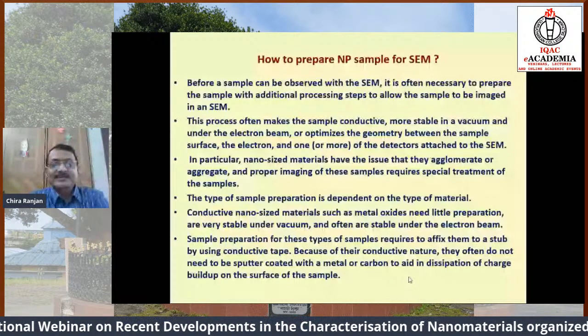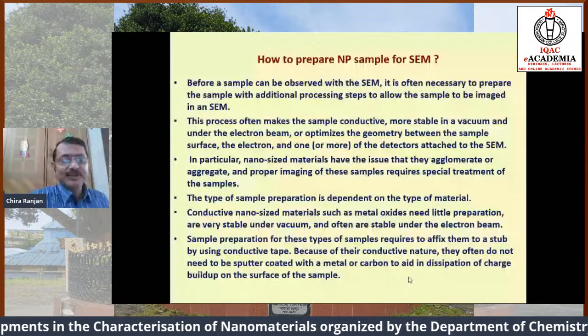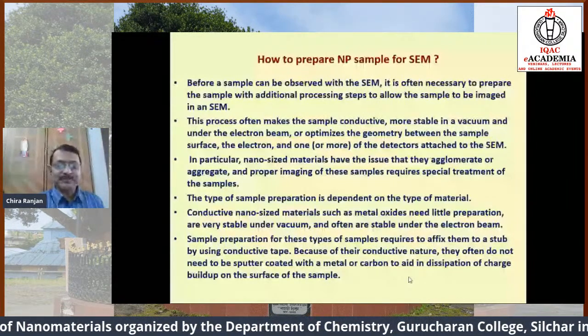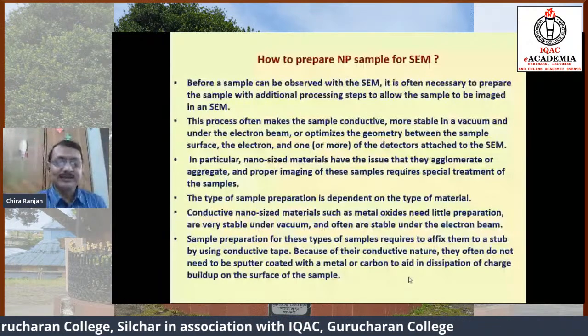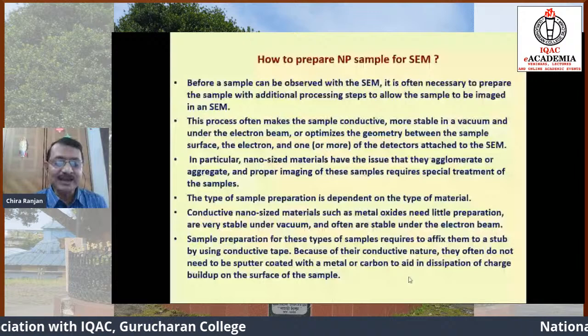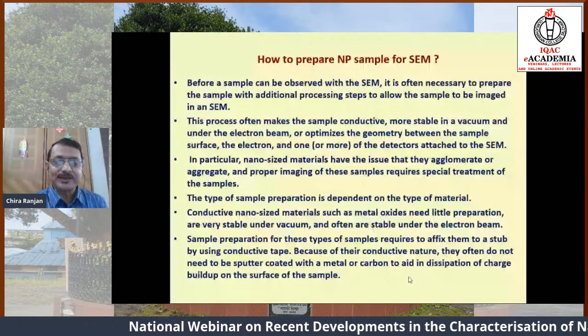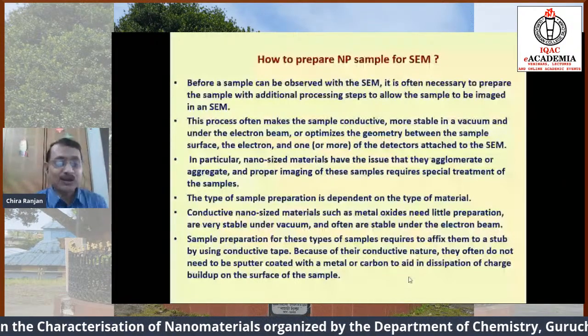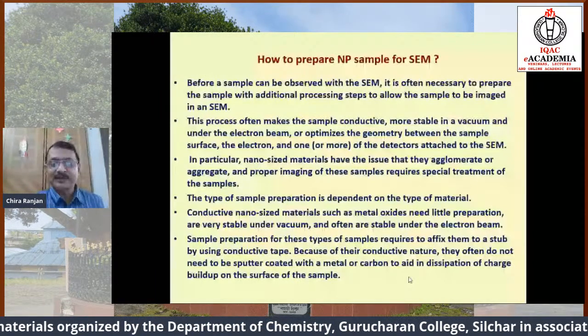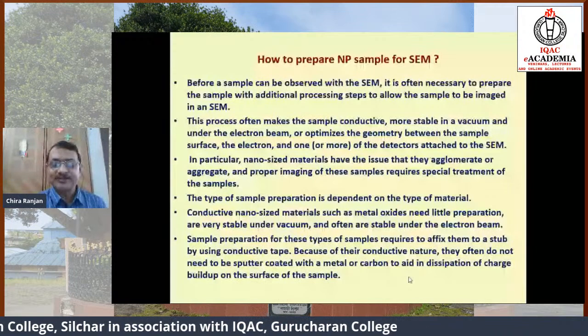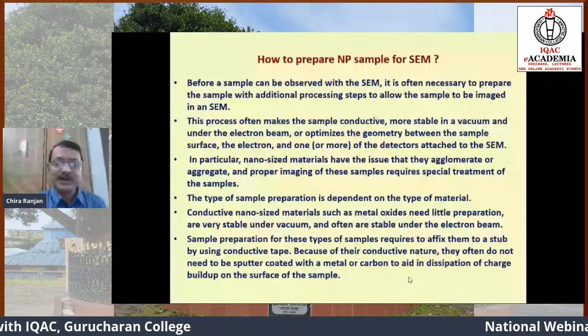Conductive nano-sized materials such as metal oxides need little preparation because they are very stable under vacuum. We must note that in electron microscopy, as an electron beam is used to capture the image, the entire imaging process is done under a vacuum. So nanomaterials by themselves are quite stable and quite conducting, and therefore they give very good SEM images. But not always. Sample preparation for this type of samples requires affixing them to a stub by using conductive tape. Because of their conductive nature, they often do not need to be sputter coated with a metal or carbon to aid in dissipation of charge buildup on the surface of the sample.